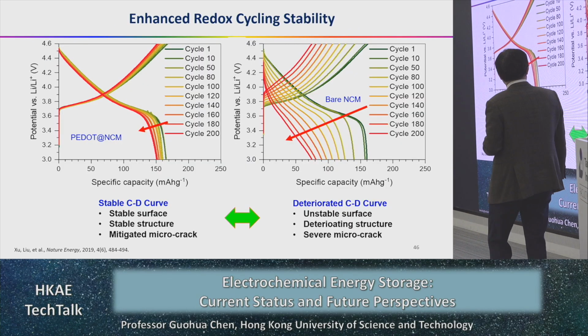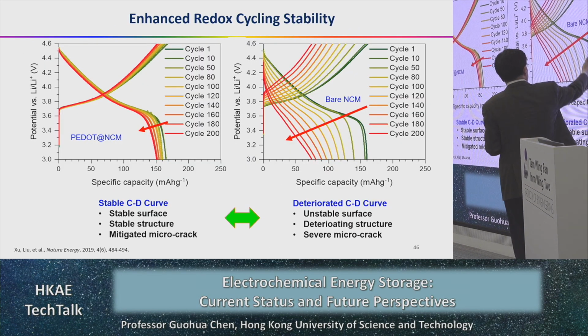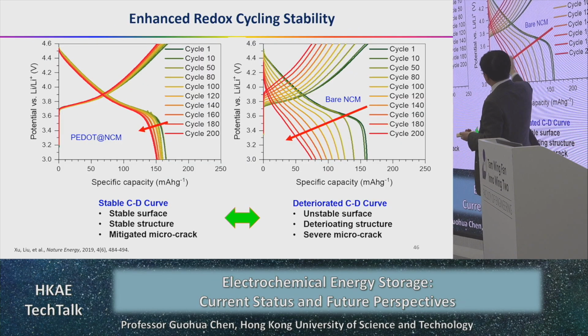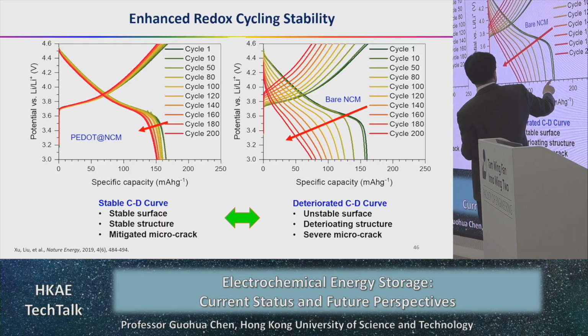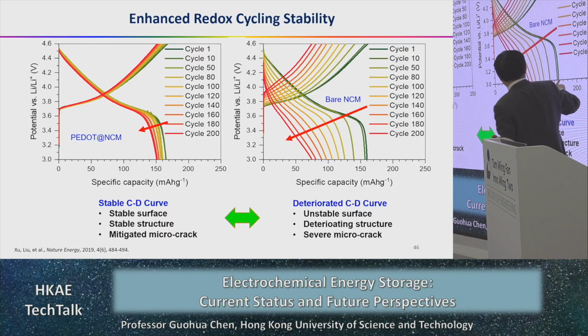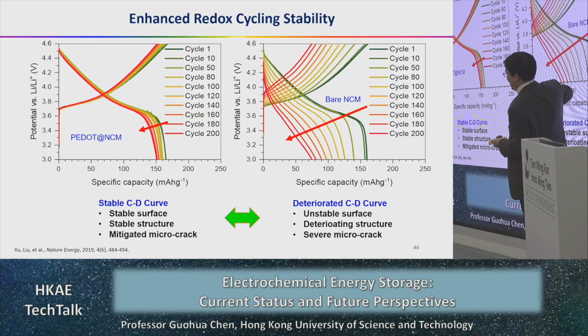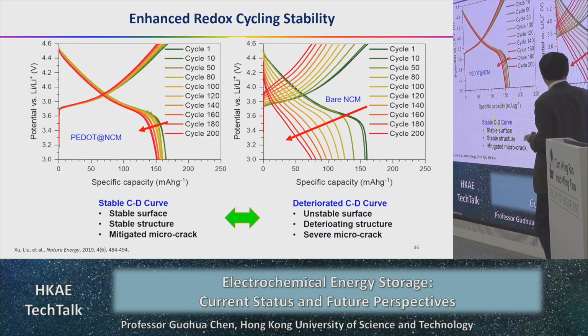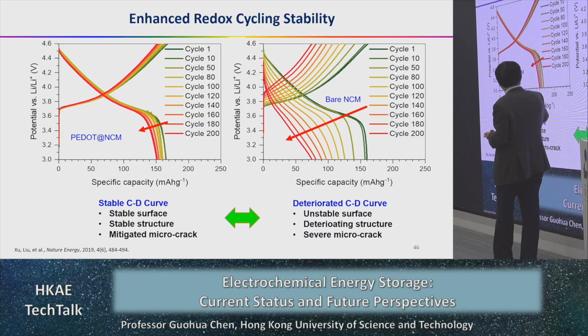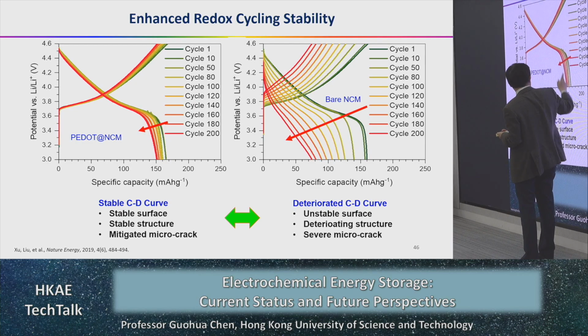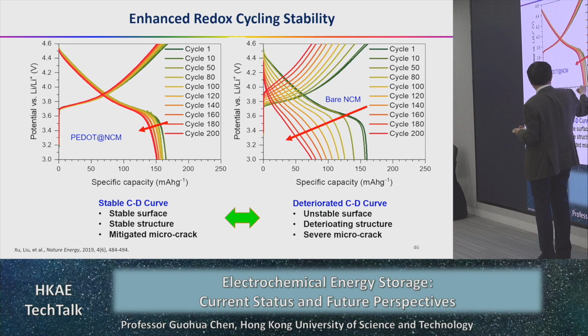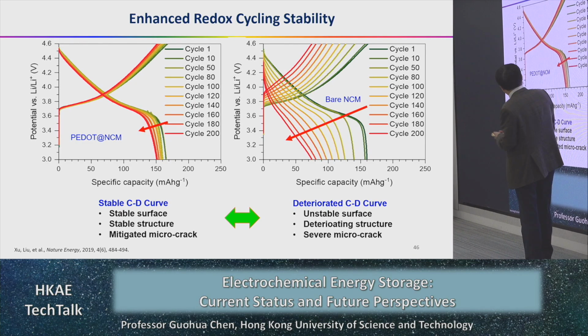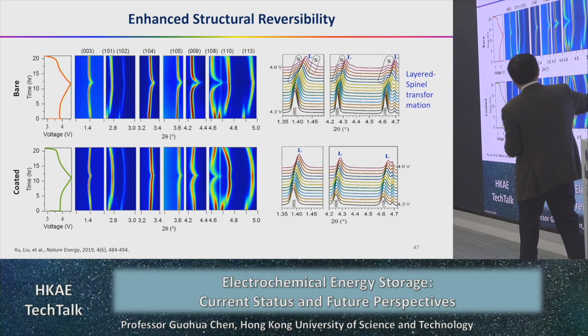And what is the effect? Without coating, that is the cycling performance. At the beginning you have this capacity. After 200 cycles, you drop to less than half. But after coating, there is still some degradation, but not that much.